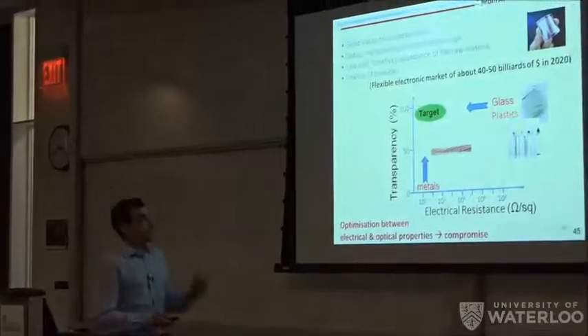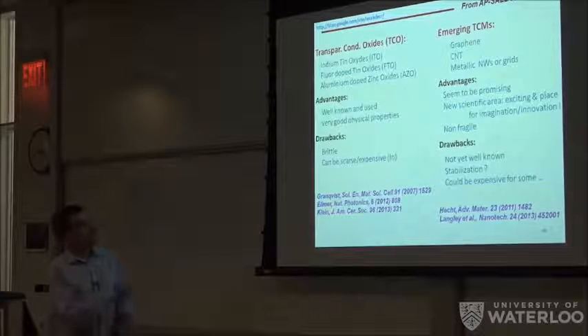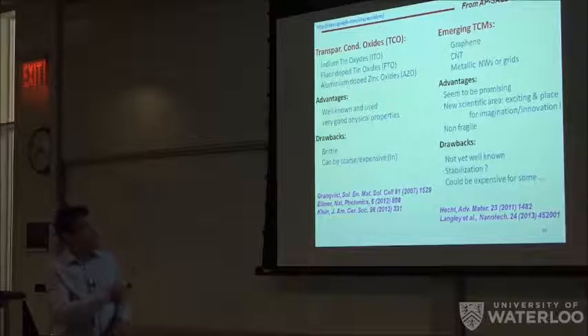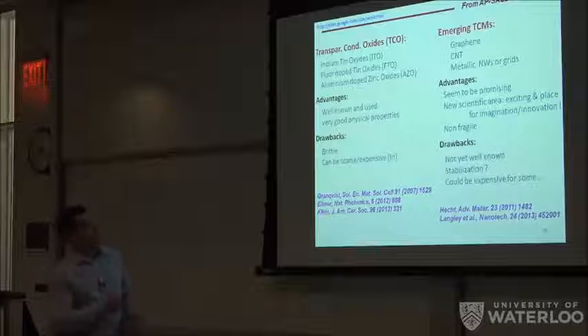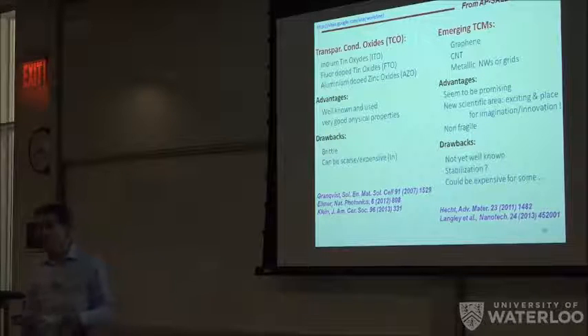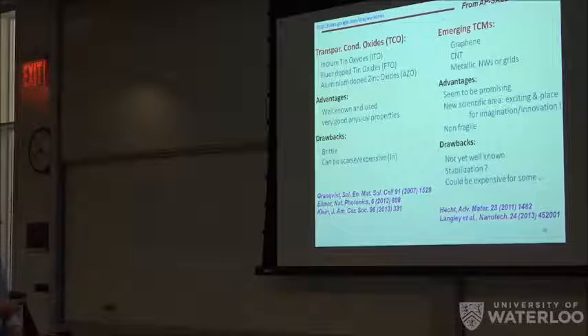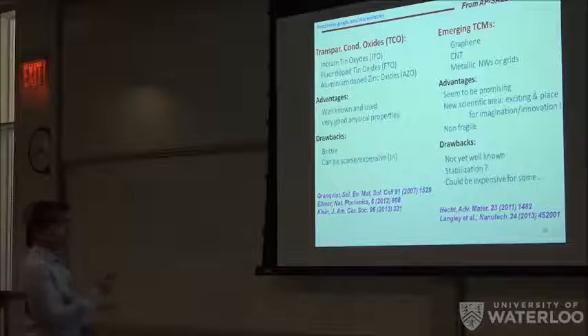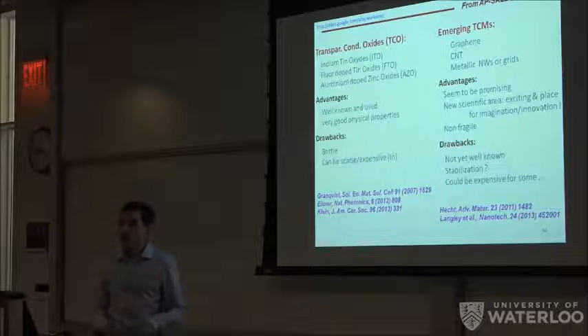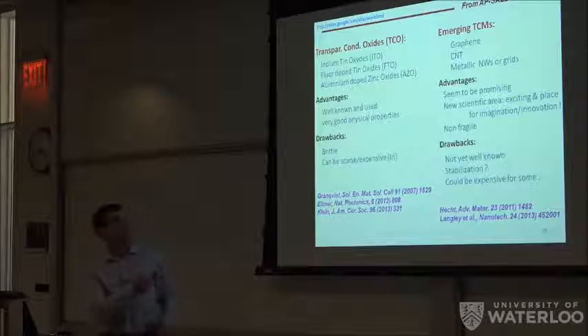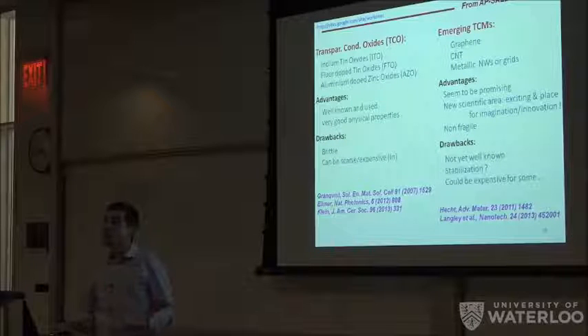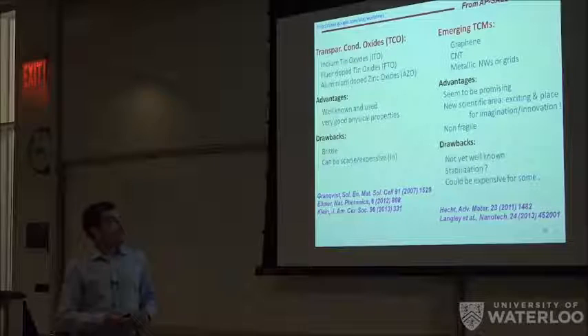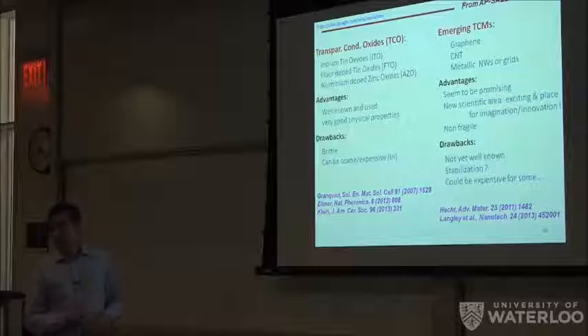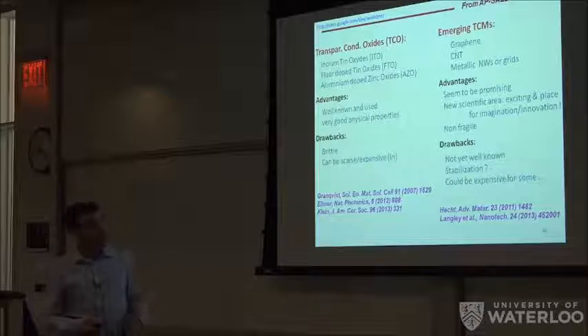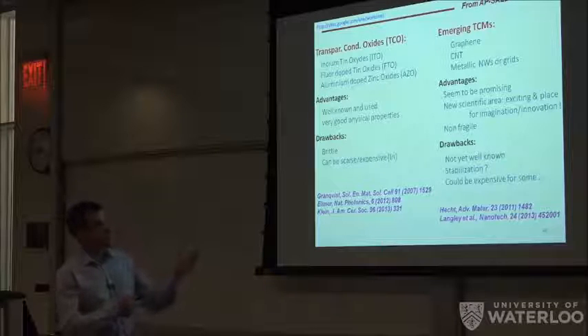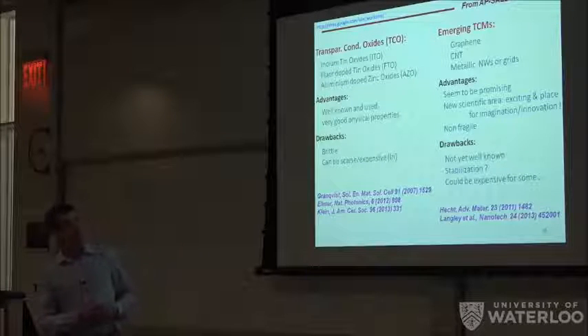So yeah, there have been different solutions that have been found so far. The most traditional one is the TCO approach, these families of oxides which are transparent and still quite conductive. And the main one is indium tin oxide. But of course it contains indium, so it's rather expensive. Indium is not abundant, so it can imply a problem for widespread use. And also these types of materials are brittle, so for flexible applications, there are alternative materials such as graphene, carbon nanotubes, or metallic nanowire networks.